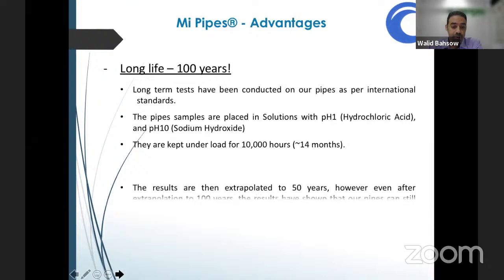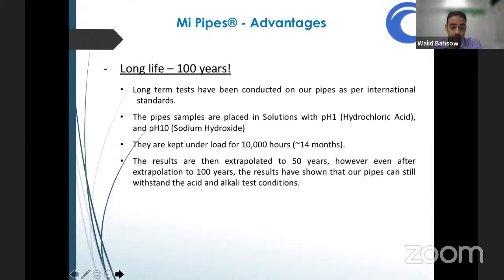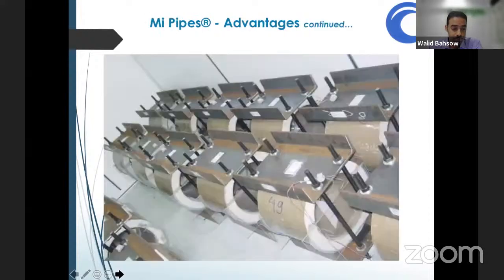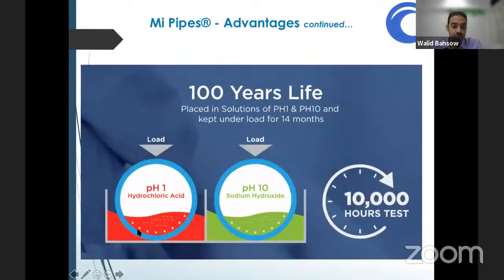So after this period, the results are extrapolated to 50 years as per the standards. However, we have extrapolated the results further to 100 years, and we've proven that our pipes can still withstand the acid and alkali test conditions. So this is a picture which shows the previous setup, which was under the ASTM and the old DIN standard. And here you can see the load is applied, and at the same time, the acid and the alkali solutions are only inside the pipes. However, as per the new standard, the internal and external of the pipe will have to be submerged in the solution, whether it is acid or the alkali. And of course, the load will be applied on top. So it is even more rigorous.